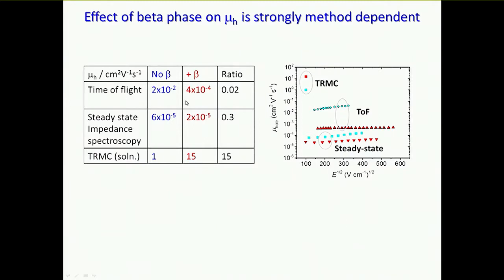And whilst in time of flight, the beta phase is a real problem. It reduces mobility by 2 orders of magnitude. In steady state measurement, it reduces it a bit. And in the most local measurement of all, it doesn't reduce it, but it increases it. How can we make sense of all of that?